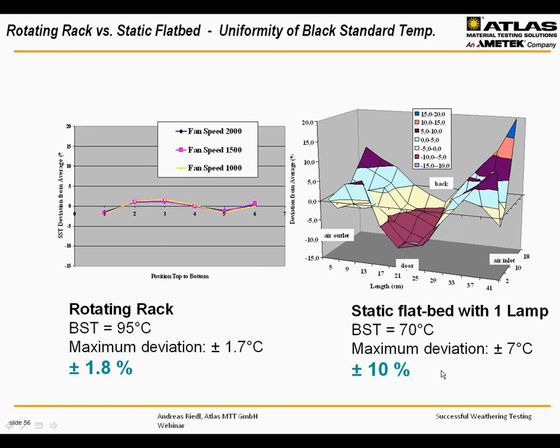Here, you have a maximum deviation of 7 Celsius if you have a black standard of 70. You see where the lamp is, you have a very low temperature. Here you have high temperatures. Why? There's an air stream here, cooling and so on, and you don't move it around. There are no means to actually make the temperature more uniform over the sample area. So some manufacturers offer small specimen trays that you have to rotate at a certain frequency. You have to take care that the samples rotate from one position to the other. But if you get much more temperature than you think, maybe 5 or 10 or 15 or 20 more than average, you may get a problem, distortion of the degradation mechanism if you have a very sensitive material or sensitive product here, so take care.